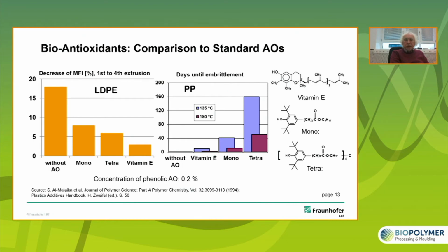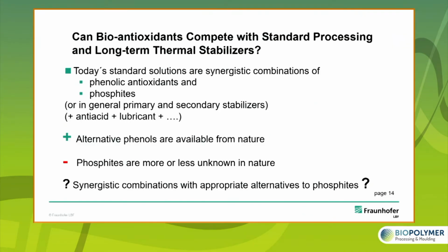If we add the normal antioxidants mono and tetra at 135 degrees, with these tetra substituted products, we have 160 days until embrittlement. So an increase compared to the material without additives. Also, vitamin E leads to an improvement, however, only to 10 days. So we conclude that the natural antioxidant vitamin E is a very good stabilizer when it comes to processing, but it is not good for stabilizing long-term products.